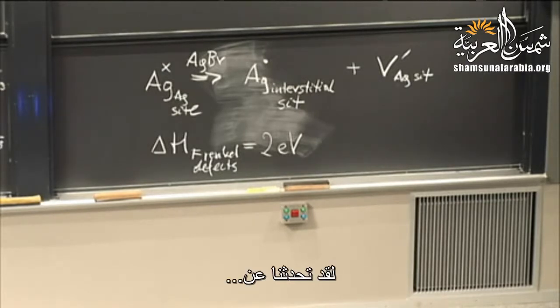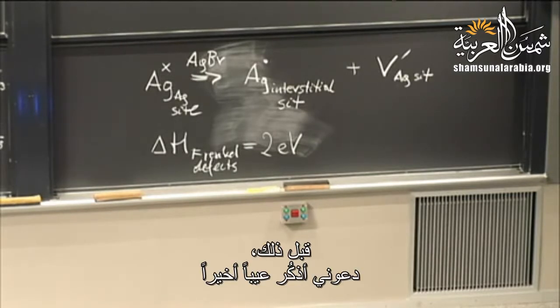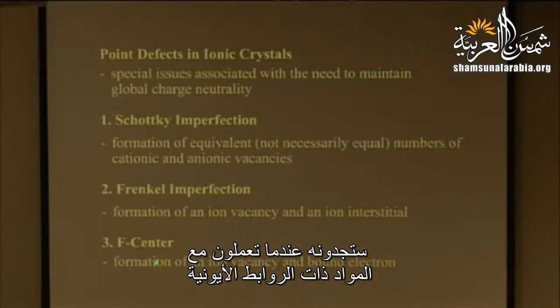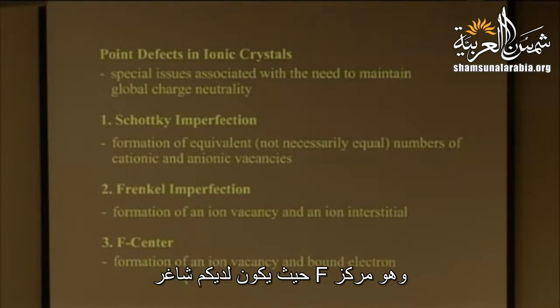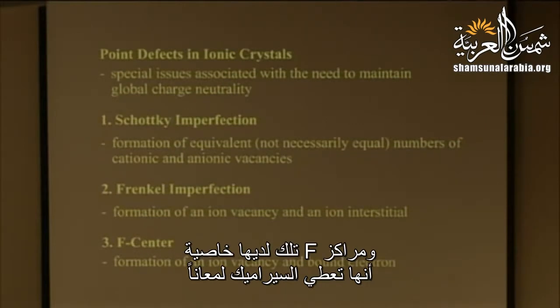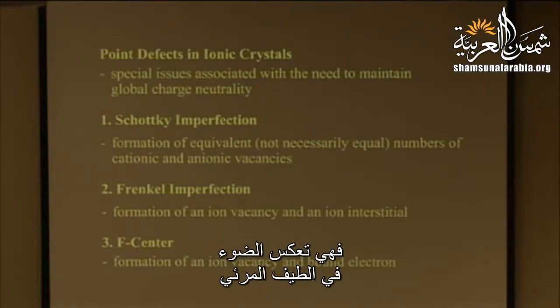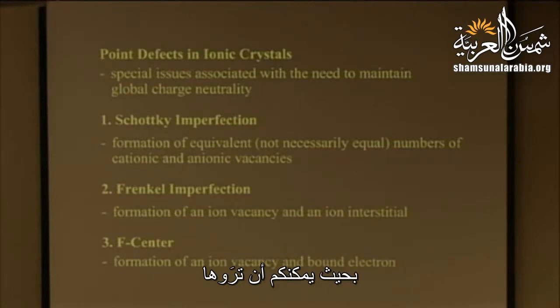So we have gone through these various defects. Before I go on, let me just mention one last defect that you might run into if you work in ionically bonded materials. An F-center is a situation where you have a vacancy with a bound electron inside of it. And F-centers have the property that they give ceramics a tint, a hue. They actually scatter light in the visible range so you can see them.